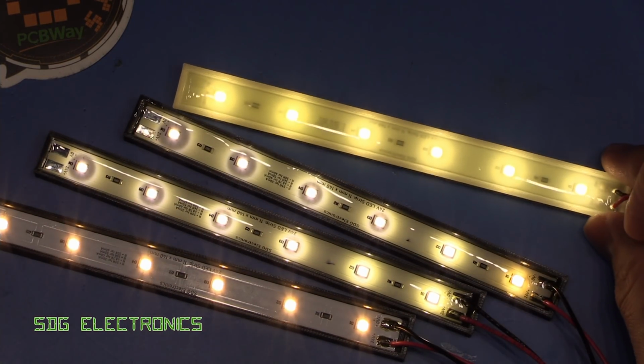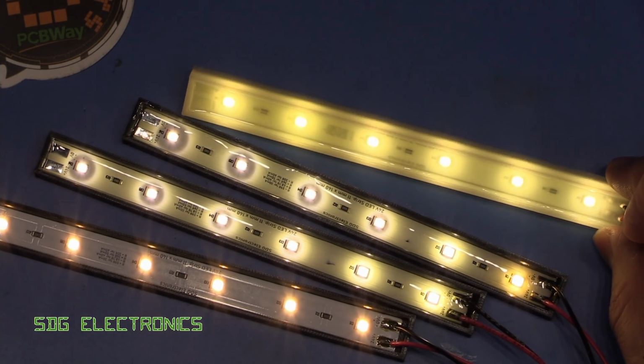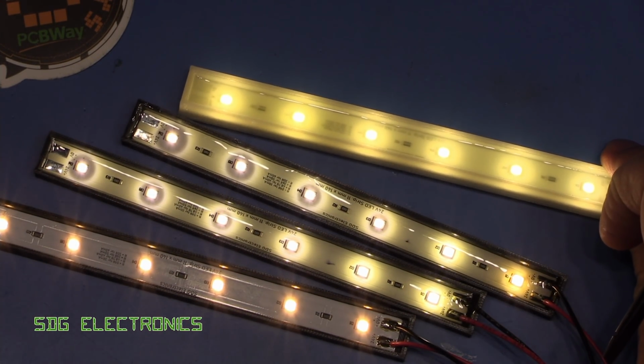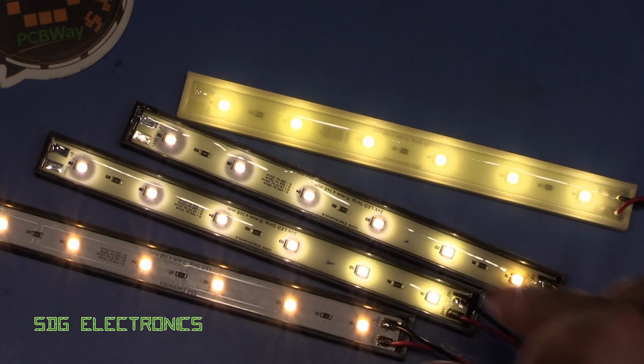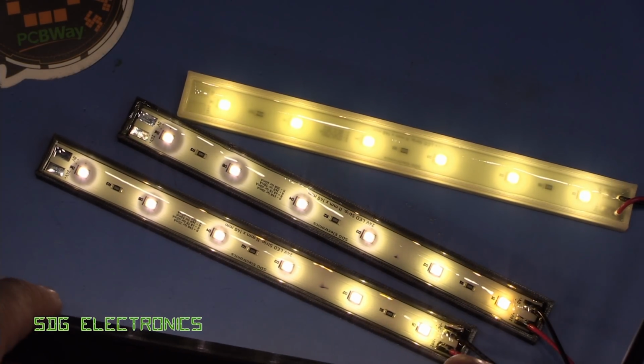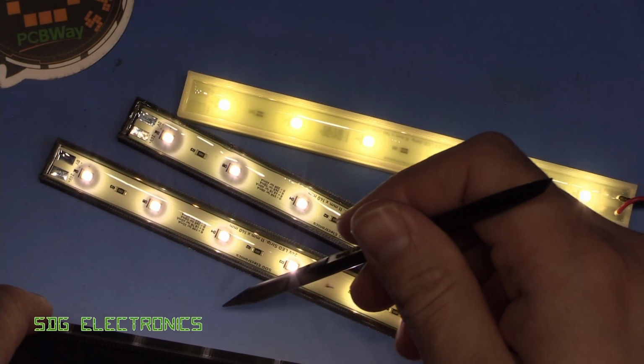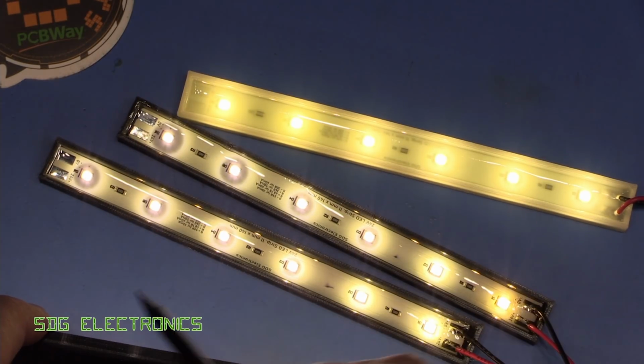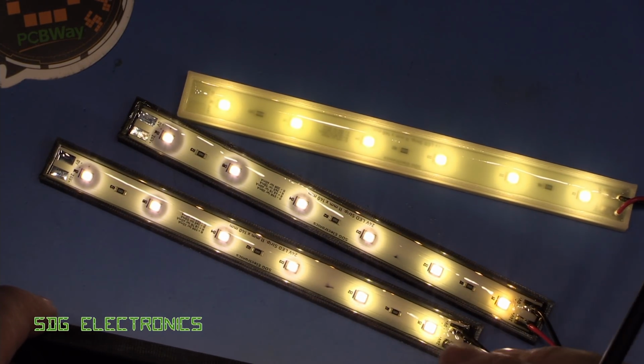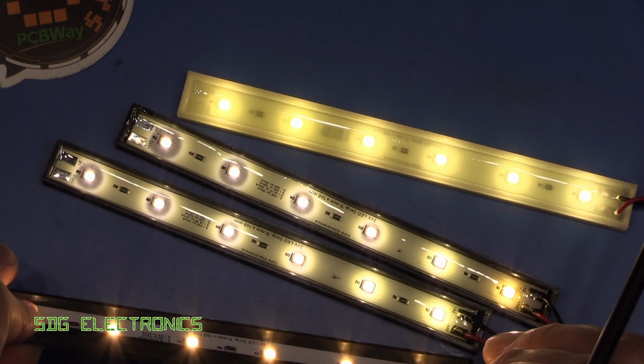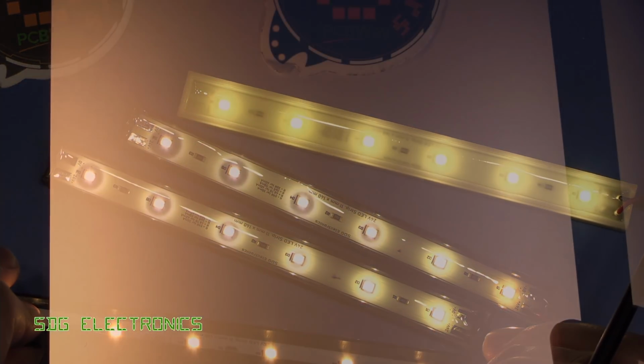And then the one with the glow-in-the-dark pigment, certainly not cooler, but it's got sort of a little green hue to it, probably because the glow-in-the-dark powder is actually fluorescing. So what I'm going to do is get the spectrometer, and I'll probably shine these onto a piece of white paper and then have the optic fibre pointing at the paper, so we get quite a good reading overall of what the spectrum is coming off these LEDs.